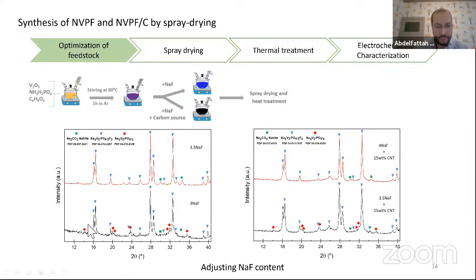For example, for the pure material, when we add only the stoichiometric amount of NaF, which is the source of sodium that we use here, we can see that we have many impurities. But when we increase it to 3.5, we can see that we have only this sodium carbonate, which we can remove easily by washing the material in water. We also prepared the material with carbon nanotubes, and we can see that with the addition of 3.5, we still have many impurities. We increase it to 4, and we have an almost pure material, with only a few traces of sodium carbonate that, as I mentioned, we can easily remove by washing the final product in water.